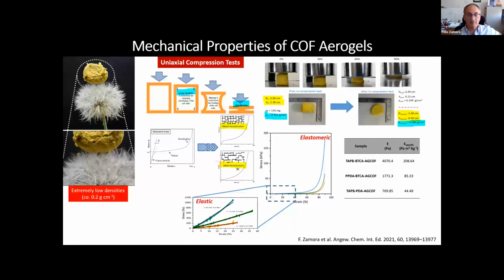So another interesting aspect that we observe during the characterization of our monoliths is the following. We were trying to characterize the mechanical properties of the monoliths by compression, okay? And what we observe, compressing the monoliths, as in here, is that when we apply a relatively low strain, below, let's say, 30%, we enter into an elastic and reversible regime. So this is reversible. While when you apply a further strain, you pass from elastic to elastomeric.